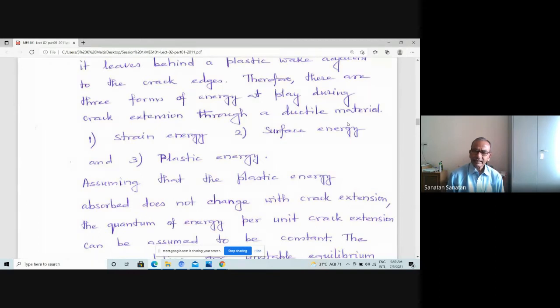Earlier we were just considering that the strain energy gets released and goes to the creation of new surface. Two forms of energy were there, but they consider that it's not that way. You deform the material, and therefore you are inputting strain energy in the body, and then near the crack tip, before the propagation takes place, it gives rise to plastic deformation. Plastic deformation is an irreversible process, and it absorbs some energy. So before the crack propagation, plastic deformation will take place, and some amount of energy will go into that zone which undergoes plastic deformation. So rather than having two forms of energy during crack propagation, strain energy and surface energy, there must be the plastic deformation. Therefore three forms of energy come into the picture during crack propagation, and the model given by Griffith was amended.